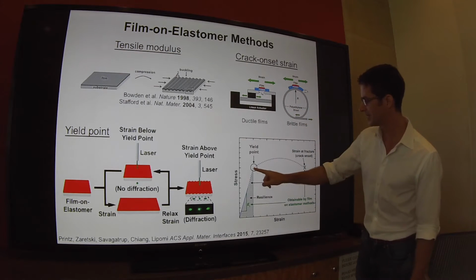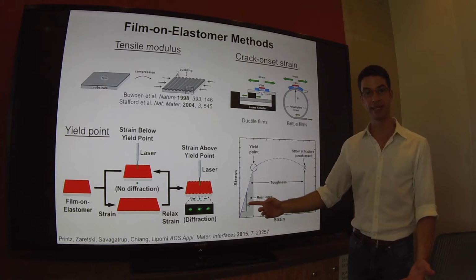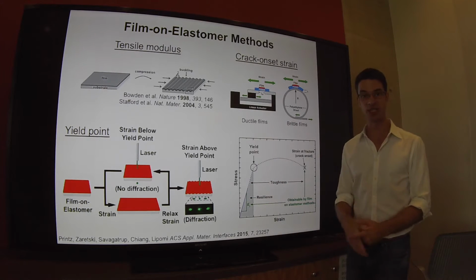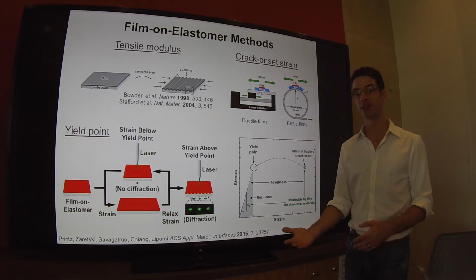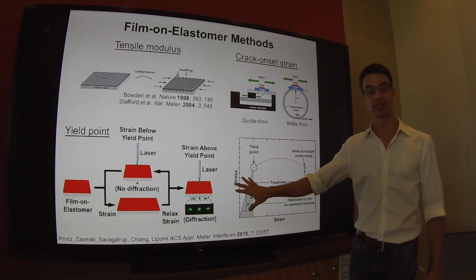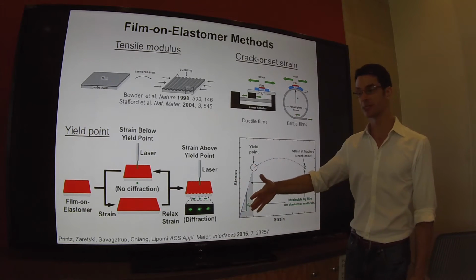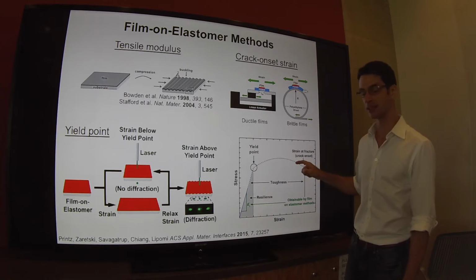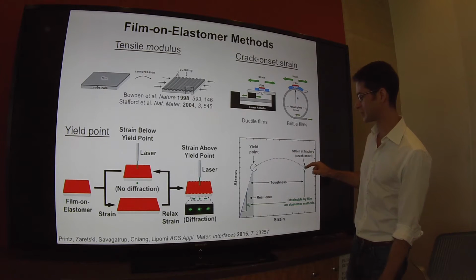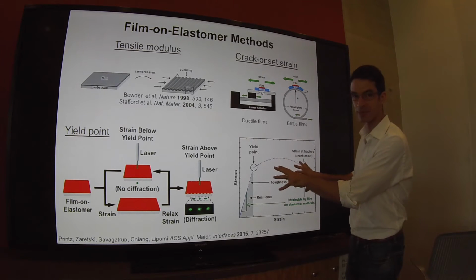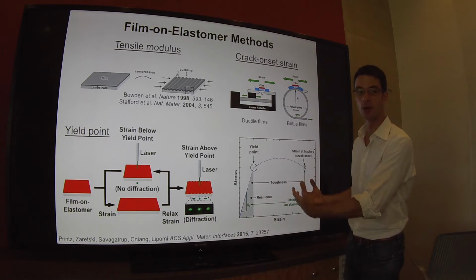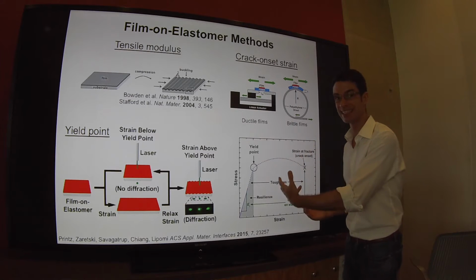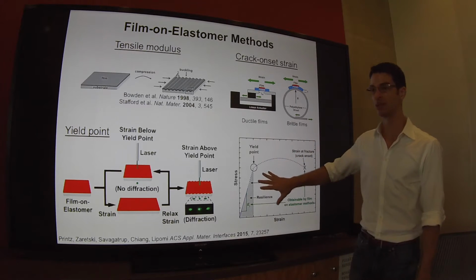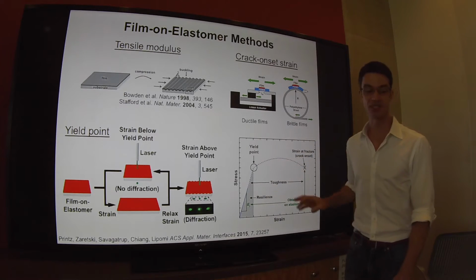Now the area under the curve here is the resilience. That's the amount of energy absorbable per unit volume by the material in its elastic regime. When that amount of energy is surpassed, then the material plastically flows. And if, assuming this point is not way up here or way down here, we can get a rough estimate of the toughness, that is the total amount of energy density absorbable by the material until it finally fractures.